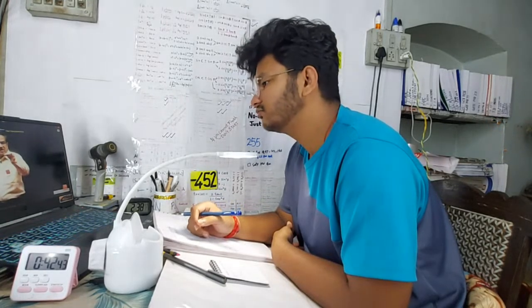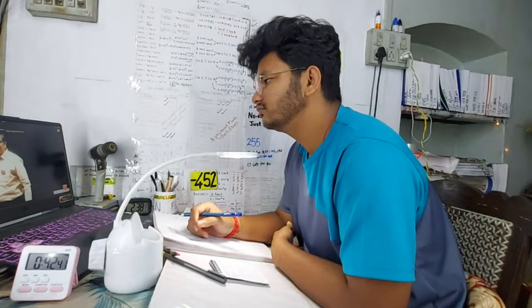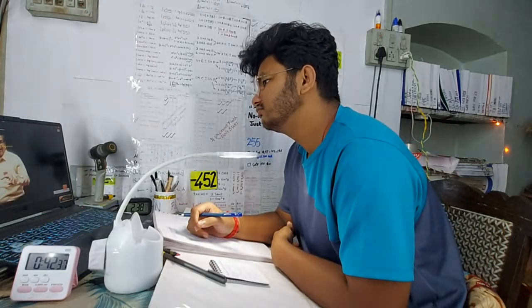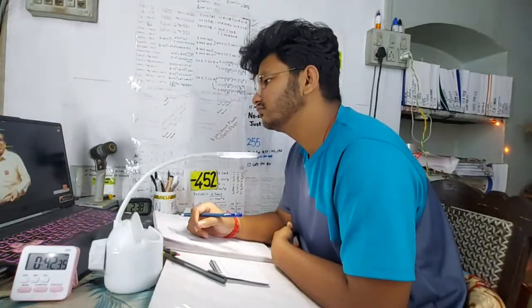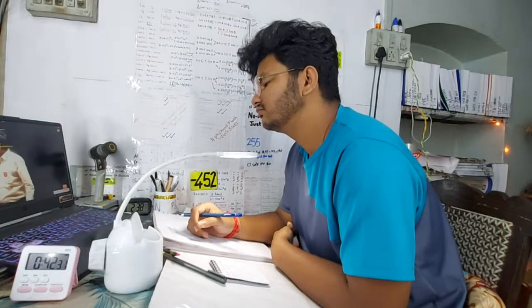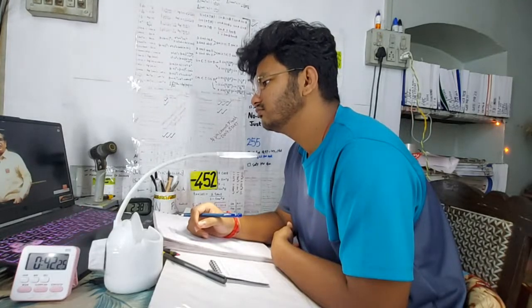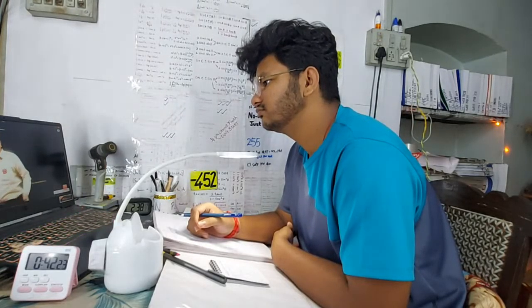So 0 seconds is the time at which rapid cooling is done and constant temperature holding is done. B1 seconds is the time at which the transformation has begun. E1 seconds is the ending time of austenite transformation into pearlite. These are the 3 data points taken. Similarly, repeat this experiment at various other temperatures like 600, 550, 400, 300 degrees centigrade. You generate data by rapidly cooling to different temperatures. Say for example, I am trying to show you here.